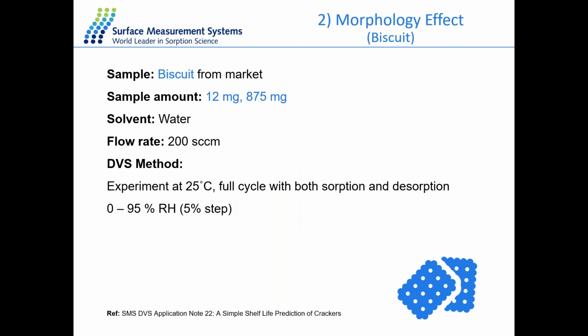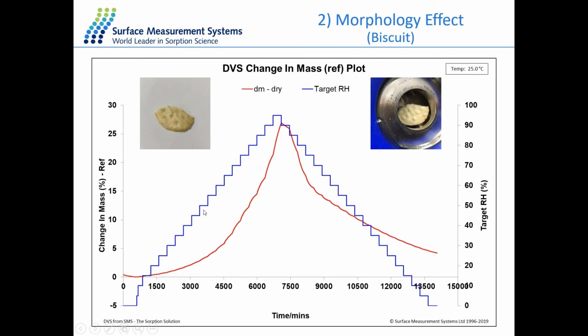So in the first case study, we have the biscuit from the market, and we cut 2 different pieces for the biscuit with different sample mass, one with about 12 milligram and another biscuit about 800 or 900 milligram. And we performed the water sorption experiment at 25 degrees with the full sorption and desorption from 0 to 95% RH with 5% steps. And here's the result for the larger piece, about 800 milligram.